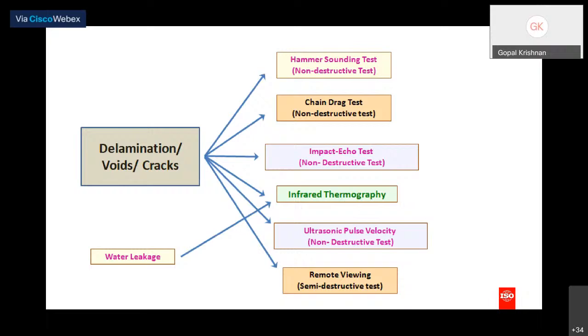Or the hammer sounding test, chain drag test, which I have shown to you. Then the impact echo test to understand the uniformity, whether any delamination is there or voids are present below. Infrared thermography to understand not only the delamination but also the source of water leakages, and ultrasonic pulse velocity, and remote viewing through sensors and all. That sometimes may not be applicable. We may also insert sensors at critical locations and keep monitoring through GPS. So that is remote sensing. All these parameters we can select.